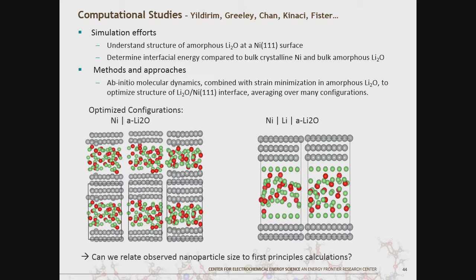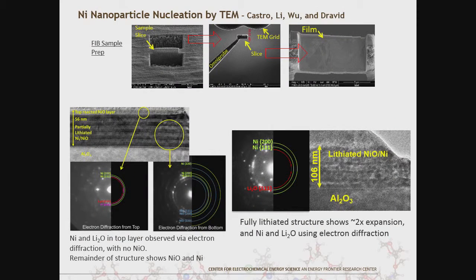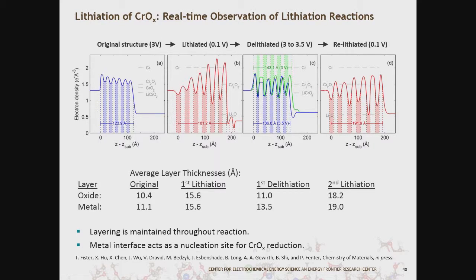Well, to give you a sense, if you look, these are in angstroms, like for this particular one. Typically, the layers are tens of nanometers, 5 to 10 to 20 nanometers. Individual layers are a few nanometers, things of that sort. So they're above molecular dimensions, but hopefully in a regime where the presence of the interfaces will be known.